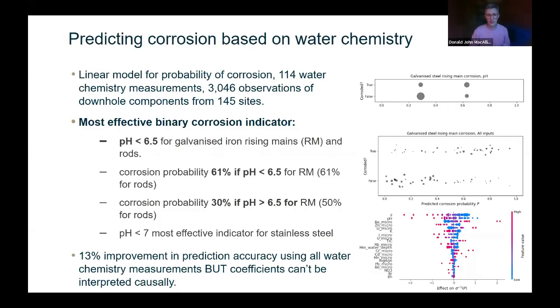And what we found was that pH 6.5 was the most effective single binary indicator for predicting corrosion. We found that the probability of corrosion when pH is less than 6.5 is 61% for rising mains, similar for rods. And the corrosion probability when pH is greater than 6.5 was 30%. So while this pH threshold of 6.5 is an effective indicator, it doesn't mean that when you have a pH above that you're not going to see corrosion occurring.